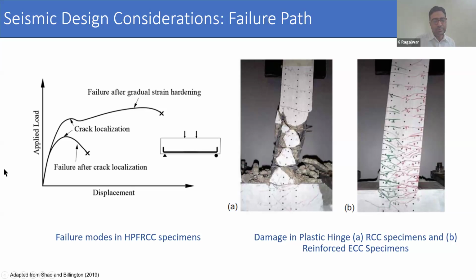At this X. The second path is failure after gradual strain hardening. In this, reinforcement continues to gain strength even after crack localization. As a result, the beam carries additional load until crushing or buckling or reinforcement fracture occurs. So this is the additional path here. Localized cracks become wider, reinforcement shows significant hardening, and compressive damage appears, although fiber reinforcement helps restrain the spalling. These two paths highlight how the tensile and compression resistance of HPFRCC changes beam behavior compared to conventional concrete based on these two observations. So that is how it is very different.